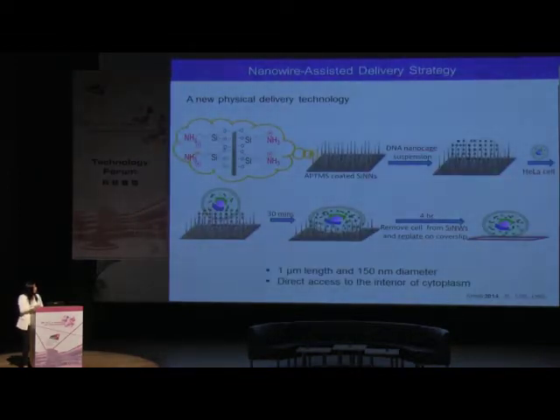And what we're using here is a silicon nanowire approach as a delivery platform. For this nanowire array, basically we functionalize it with some amine on top with positive charge. And then we put our negatively charged DNA sample on top. After that, we place the cell. And after 30 minutes, basically the cell can penetrate through the nanowire, and then our DNA sample can be released directly to the cytoplasm for imaging.